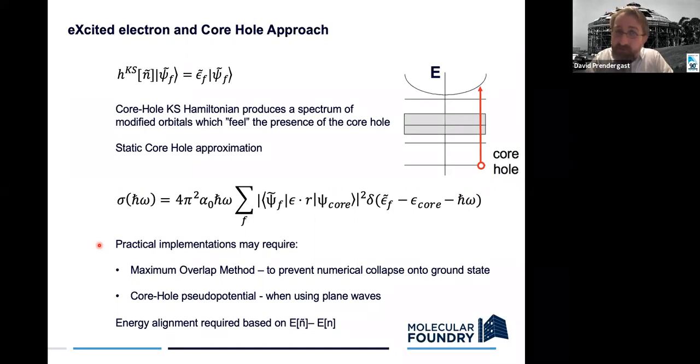And so we try to do that using a supercell, so multiple unit cells, which is a bigger calculation, but typically only about the size of a nanometer, so 10 angstroms. That's sufficient. So that's maybe 80 to 100 atoms for most crystals. So it's a doable calculation. It's not the typical cheap calculation you can do for a small unit cell, but it's doable.